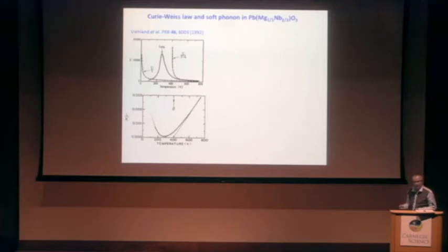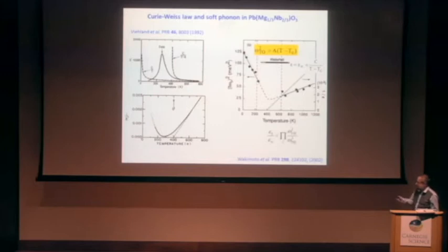I will take my laser, it is better. Because this high temperature permittivity does not exhibit any frequency dependence, one can assume that there must be some excitation at much higher frequencies, let's say above microwave, and it means phonons.